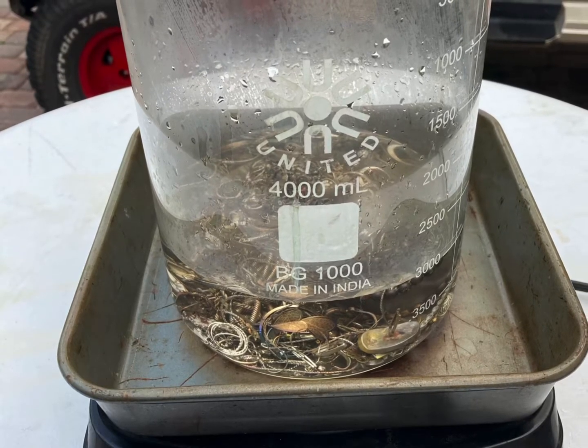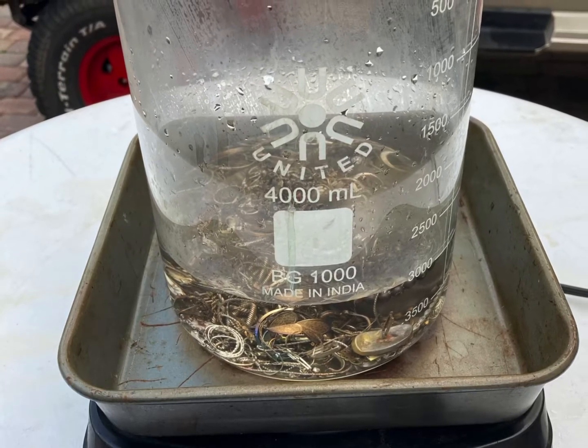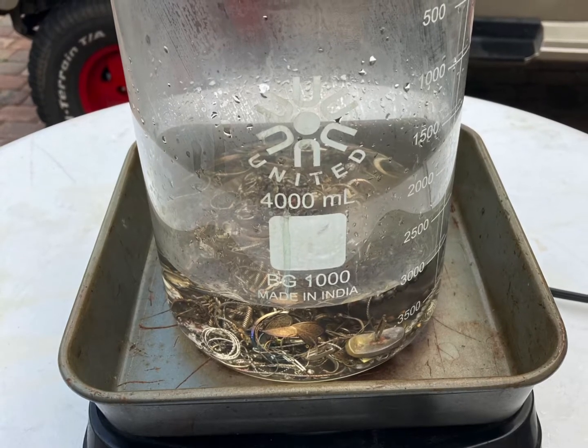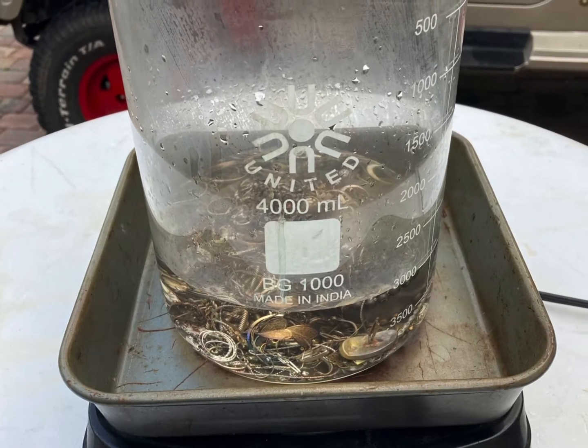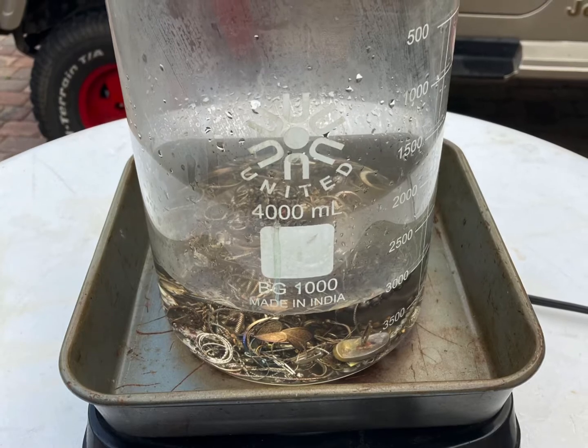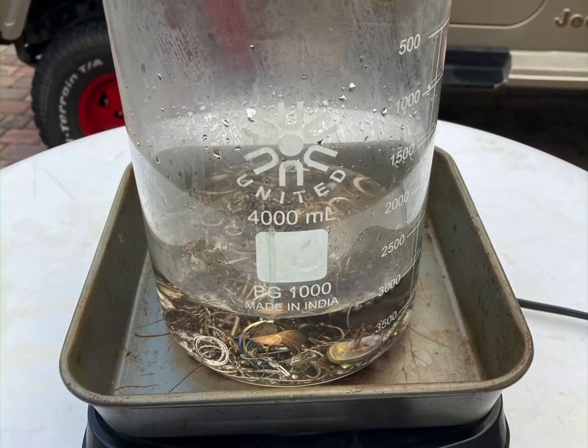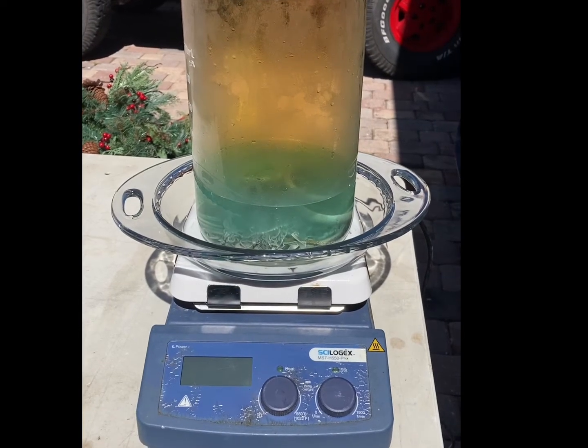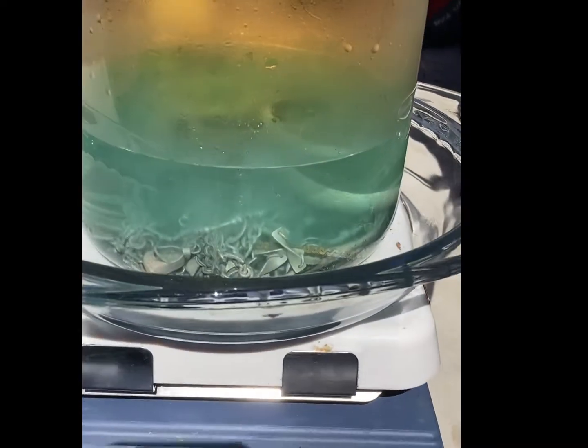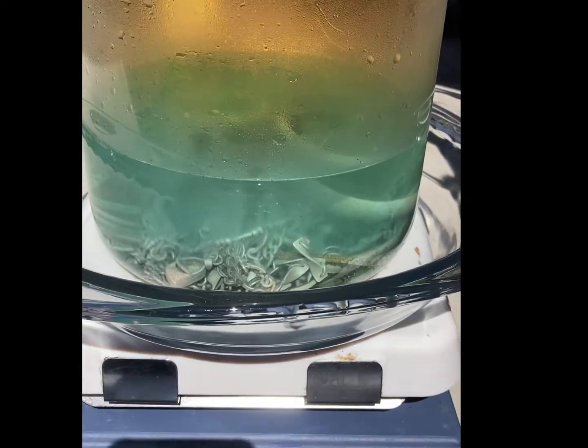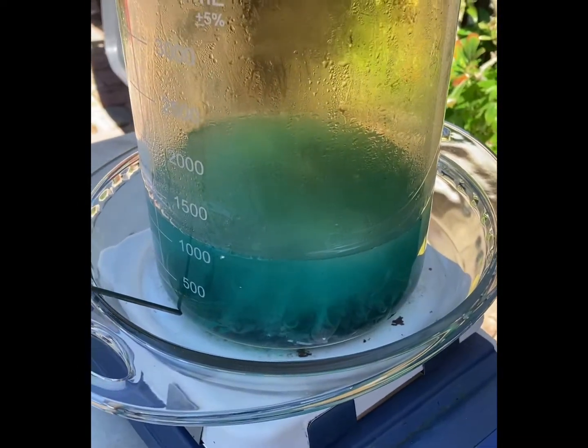Once your sterling is super clean, start by heating it up to about 180 degrees. Then you're going to add your nitric acid. You're going to start with a 10-to-1 ratio, 10 parts distilled water, 1 part nitric acid, and that nitric acid is going to be a 70% nitric acid.